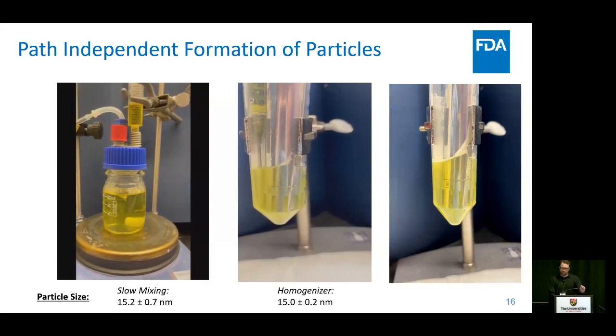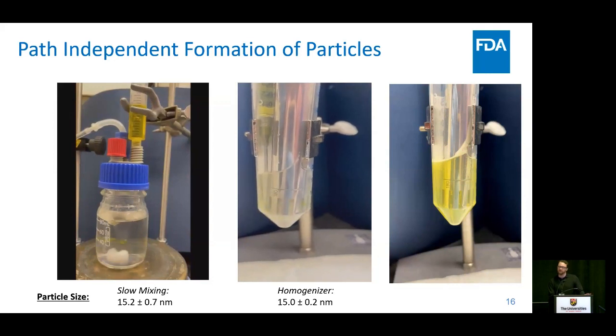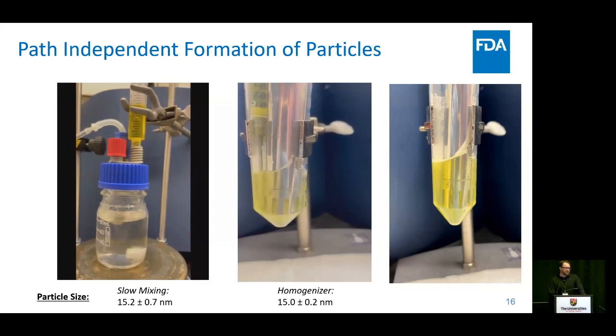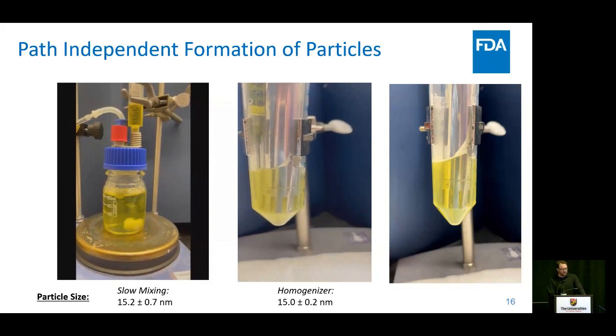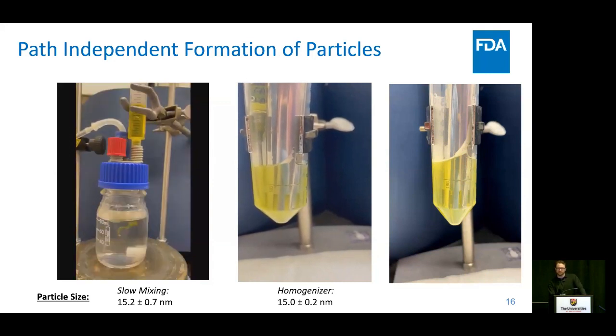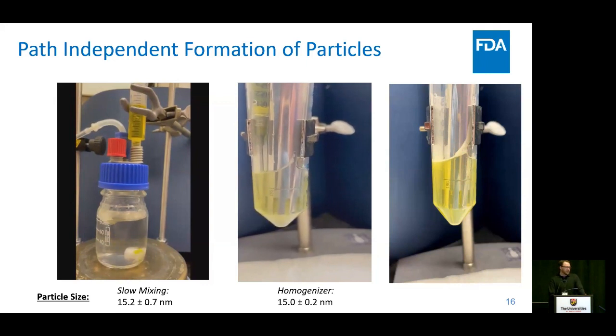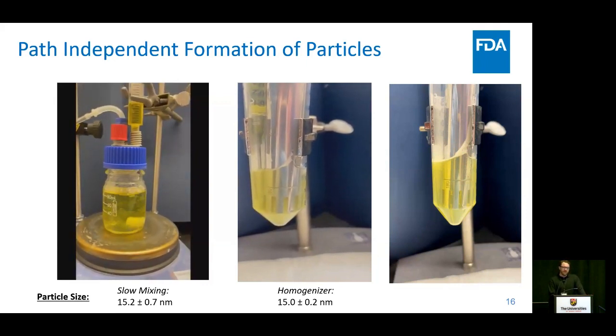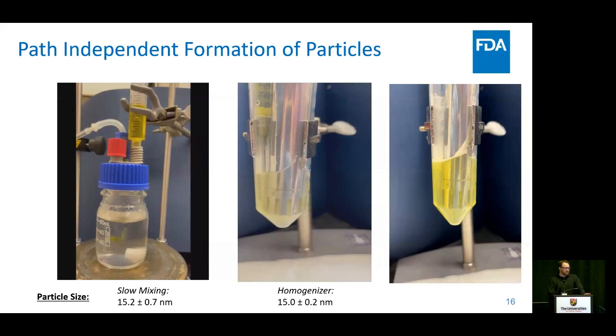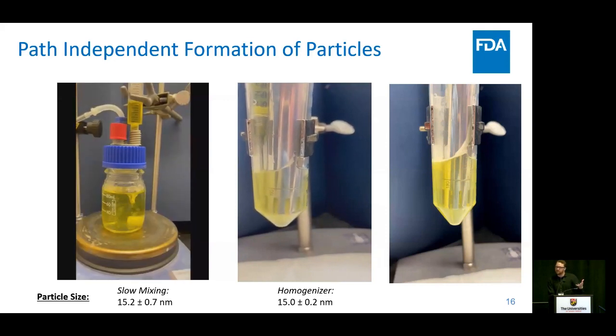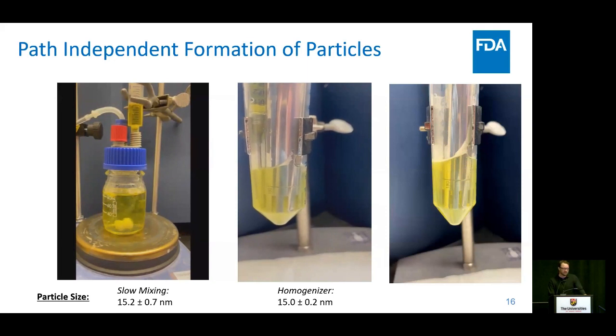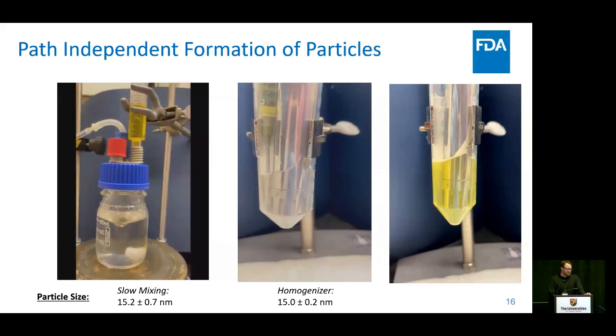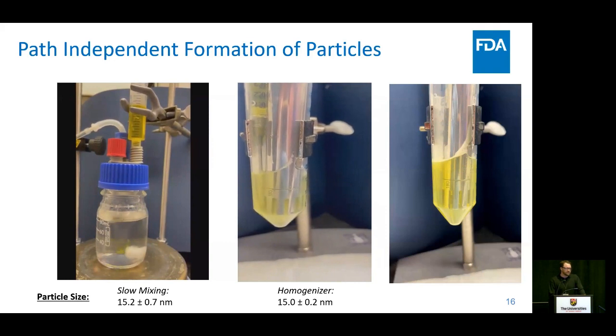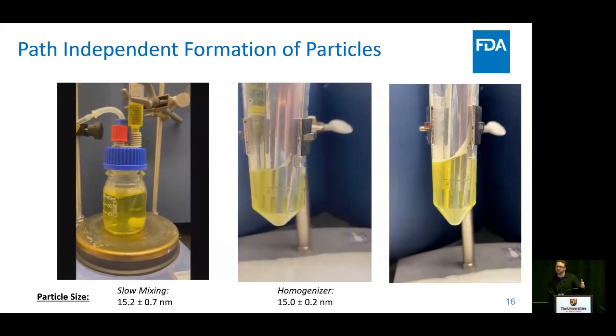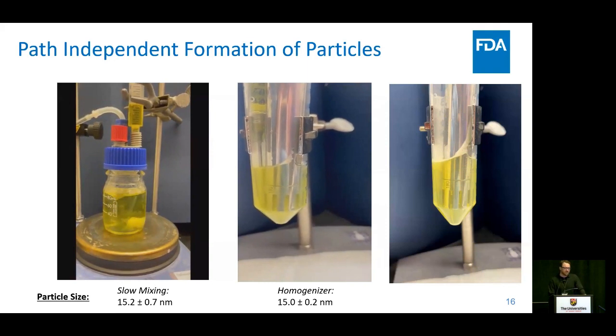Now, this is only true for one specific kind of direction. And so at that composition, everything I've showed you so far is adding that surfactant and oil into the aqueous phase and letting it disperse. If you go the other direction, something else happens, and it looks like you can form a nanoemulsion. And this is one of our questions: is this an intermediate, or is this a true state for the system? And so it seems from what we've seen that if this is a nanoemulsion, it should be susceptible to manufacturing and process changes.